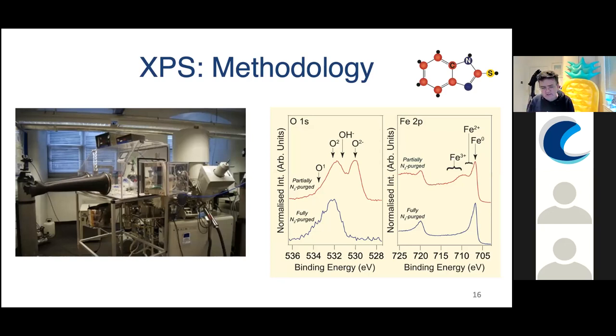So it's not oxidized. Many people have done this work, which we believe is compromised because it's oxidized following the immersion. And that's demonstrated here. So this molecule here, which I'll come back to later, is mercaptobenzimidazole. It's a well-known corrosion inhibitor in acidic conditions, and it performs really well. And we've looked at that